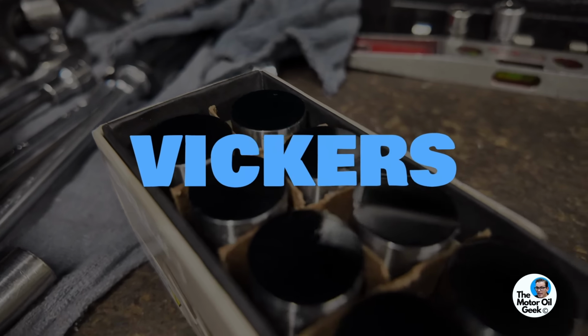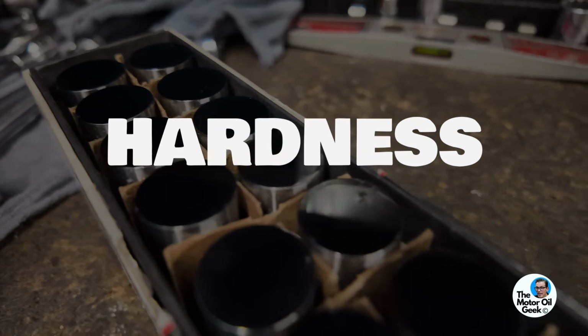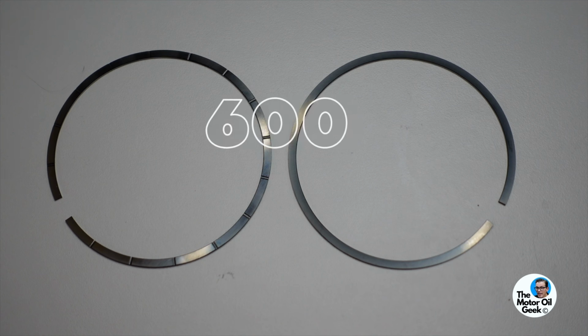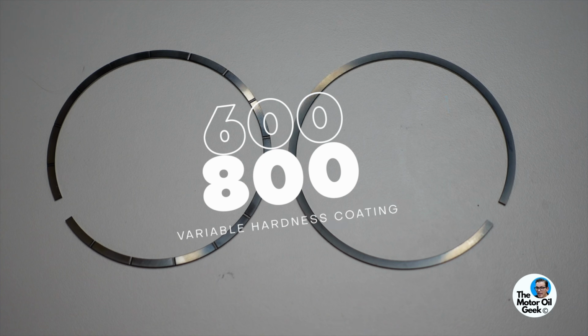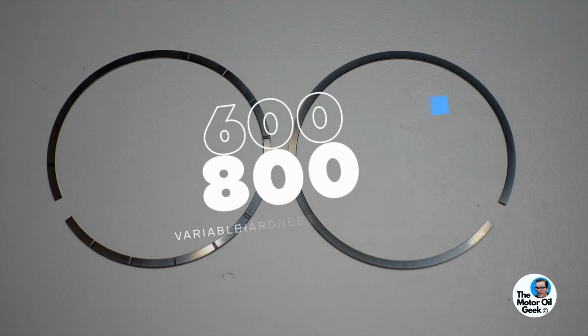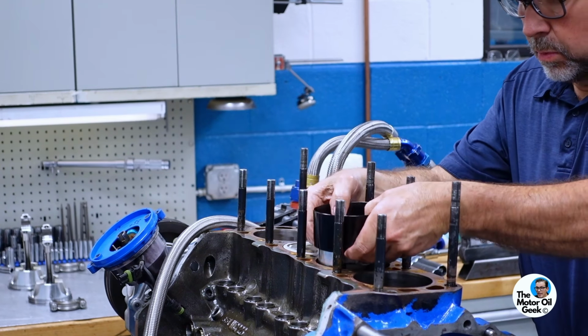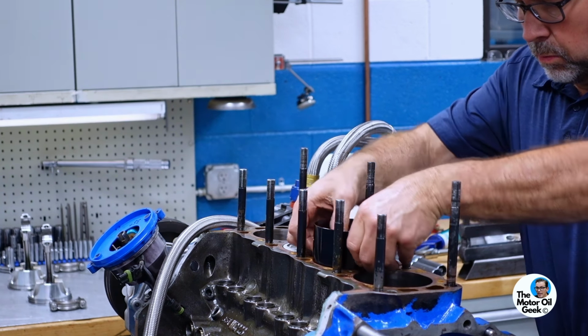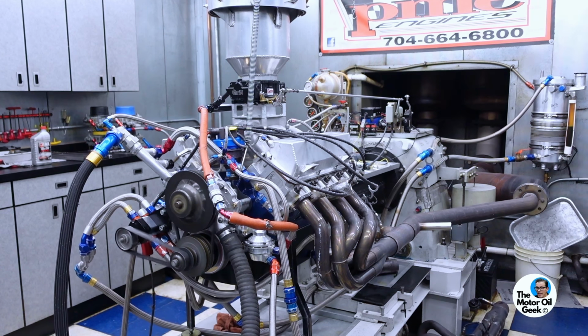So for running in, that's perfect. Well, because a DLC is like 2,400 Vickers hardness. Yes, so it's really, really hard. But with the variable hardness coating, you can make it around 600 to 800 at the start, and then it gets harder as you slowly wear through the process. So, like I said, for running in, that's perfect because you want to run in gently and knock the asperities off carefully and have a nice smooth surface without ripping them out.